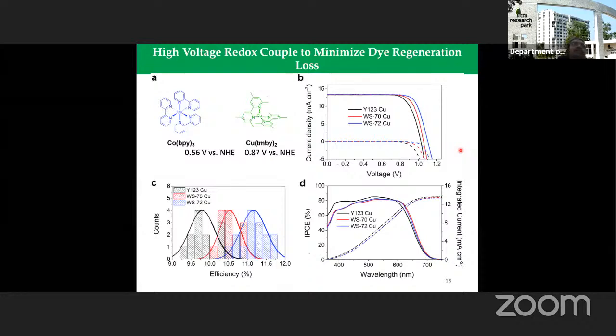Now let's look at another example. What they have done, instead of, okay the previous one was with the cobalt electrolyte, they have used copper tetramethylbipyridine based electrolyte. Why? Because this gives only 0.56 volt, whereas this gives 0.87, nearly 200 or 300 millivolt higher. So therefore, the cell which was giving 0.7 volt, if you add this 300 millivolt to that, it will give you 1 volt. That's the idea here, right?